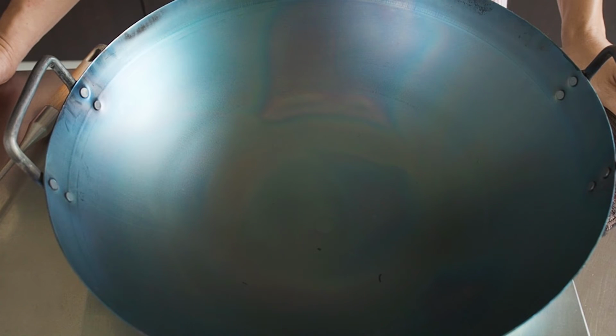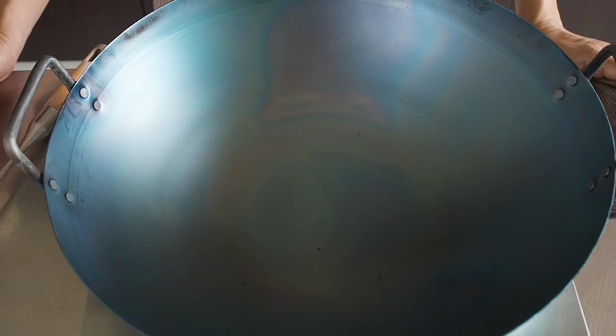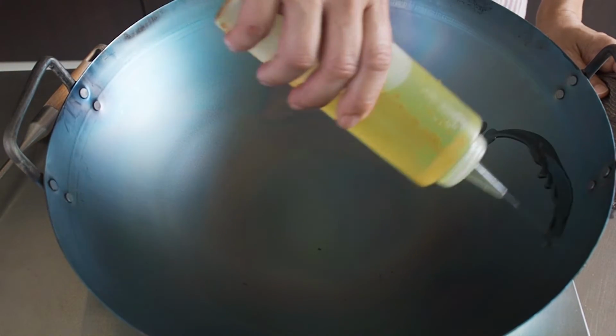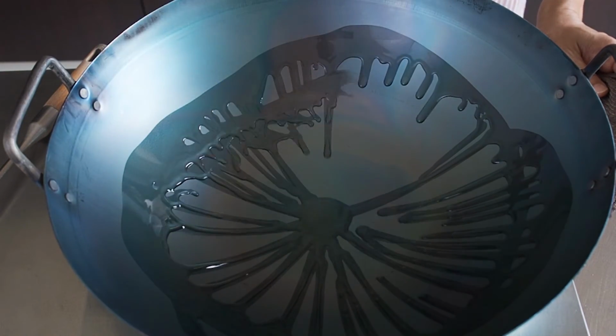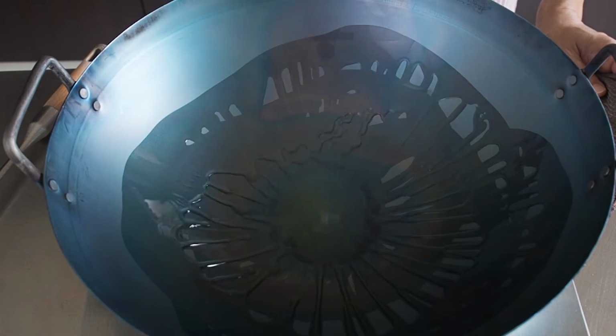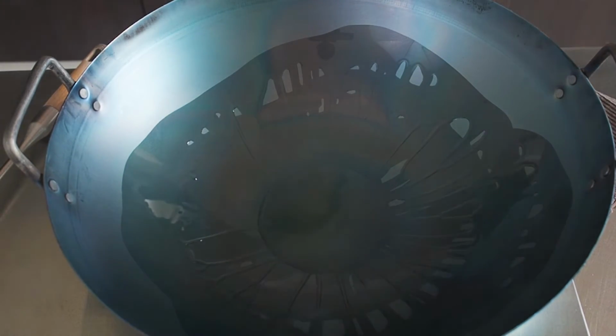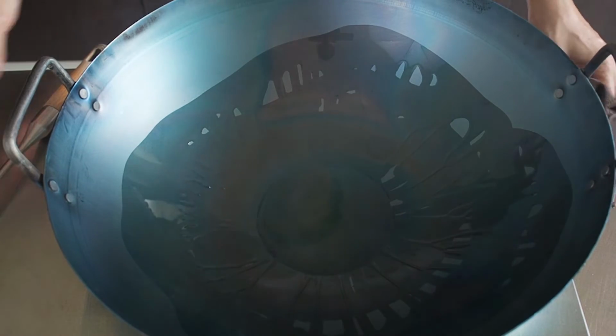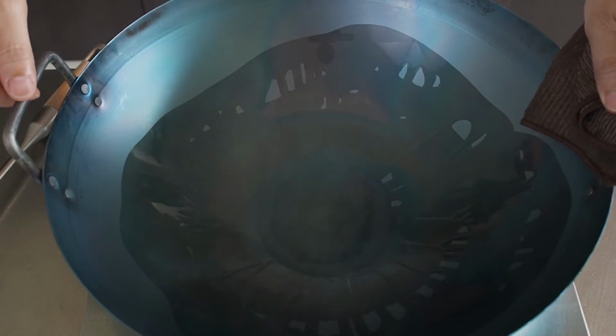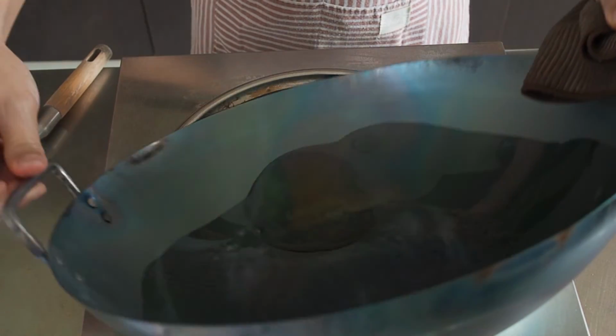After 5 to 10 minutes, when the wok has cooled off, cook a vegetable dish like you would normally using these vegetables. So, over medium heat, pour in about half a cup of oil into the pan. Coat the surface of the wok with this oil. Heat this oil over medium heat till it smokes. If you're using an induction cooker, it will take about 20 to 30 seconds. If you're using a stovetop, it will probably take you 40 seconds to about a minute.